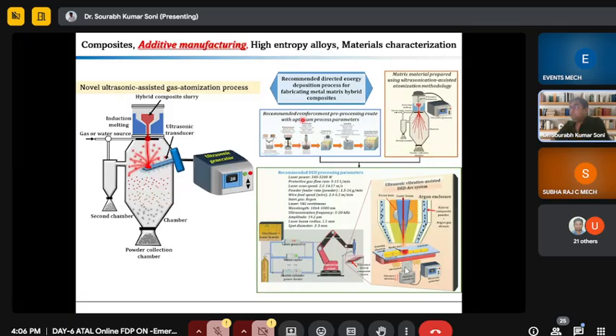Further, after the gas atomization process, we can follow the reinforcement pre-processing route, and with this route we will mix the matrix material and reinforcement particles, and further we will do the DED processing. In DED processing, what I have recommended is one heater behind the substrate material, so we will maintain the melting temperature throughout the process.